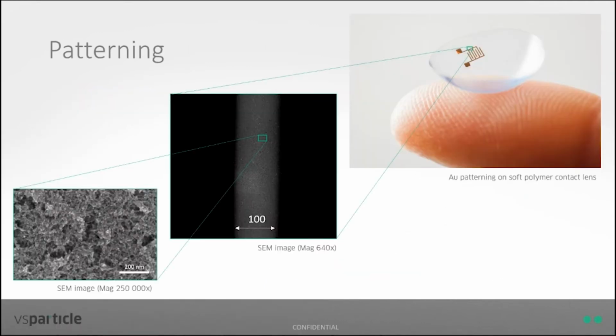So this is an overview of what you can get as a result. On the right top corner, you can see a gold pattern printed directly on a soft polymer, in this case a contact lens. If you zoom into one of these bars, you see this nice line of material deposited. And if you zoom into the material, you really see this nanoporous layer appearing. This is really what makes our process unique: if we are stacking those nanoparticles on top of each other in our printing process, you get this highly porous layer, which is really unique in different industries. It's quite difficult or almost impossible to make the same porosity using other methods.